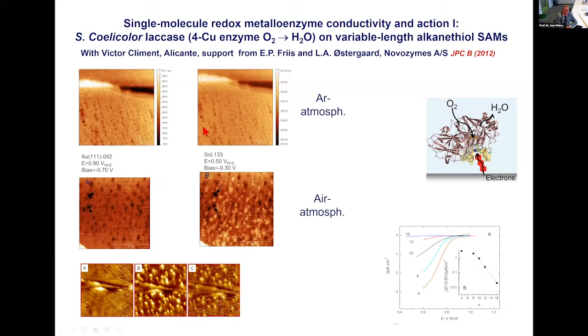The same, or rather similar thing with laccase. If there is no dioxygen, which is the substrate here, there are no pictures. Well, the pictures you can see, very strangely, are the underlying alkanethiol monolayer and the black spots, that is pits that are always formed when you have gold and sulfur together. Then you let oxygen in, and you go from the potential where the enzyme is inactive to the potential where it is active. Then all the molecules all of a sudden disappear. It is as if binding of oxygen triggers opening of an electron transfer channel that you can see in STM.